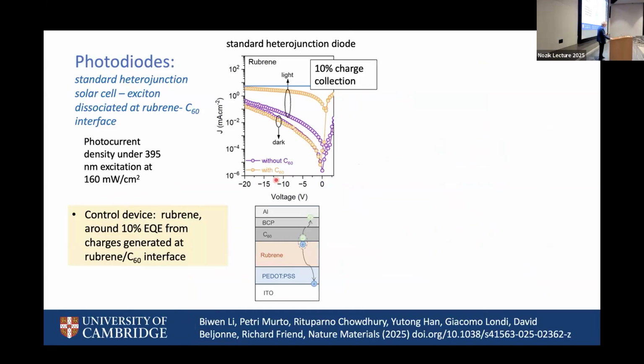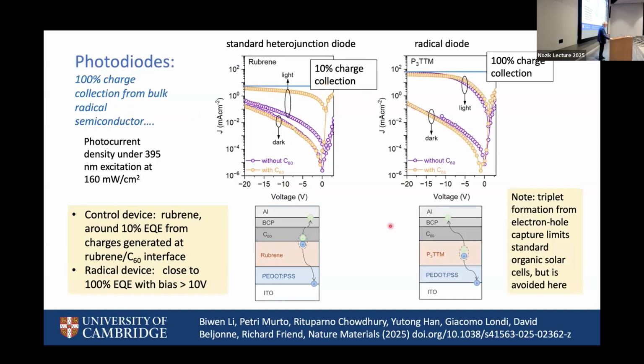I will briefly show you the placebo or comparison device where we've got a standard heterojunction, very much like the Ching-Tang device, between a donor, which is rubrene, and an acceptor, which is C60. If we absorb light in that structure, with electrodes top and bottom, it's only light absorbed very close to that heterojunction between the donor and acceptor that generates charges. So we get about a 10% charge collection efficiency for that structure. But if we now replace the rubrene with our radical system, it's now 100% radical, we essentially get 100% charge collection. We have generated electrons and holes. I have to say we need a bit of voltage to extract them, about 10 volts to get them all out.